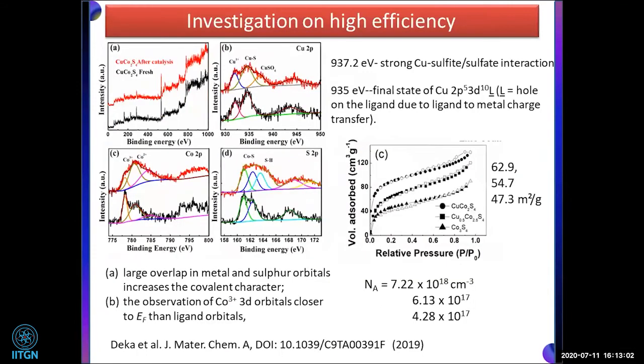From the band structure and from the XPS, we found that in this copper cobalt sulfide the electronic states near the Fermi level consist mainly of cobalt 3d and sulfur 3p orbitals. There are a few literature reports on theoretical calculations, and this cobalt 3d is more localized, and the electron density of the metal d orbital at the Fermi level is higher for this copper cobalt sulfide. So that gives us very good electron donation, and that electron takes part in the photocatalytic series.